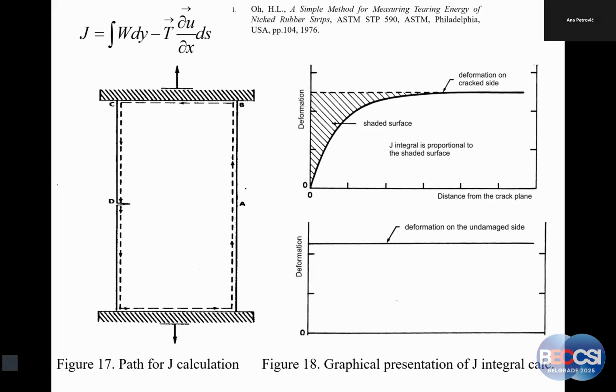So, since this way of loading and this sketch is practically the same as in a cylindrical pressure vessel, theoretically speaking, we can measure J integral just by measuring and estimating this point here and approximating this shaded area. There are some obstacles, of course, and complications which can be solved. My main message is that there is an option to measure J integral directly on a structure.